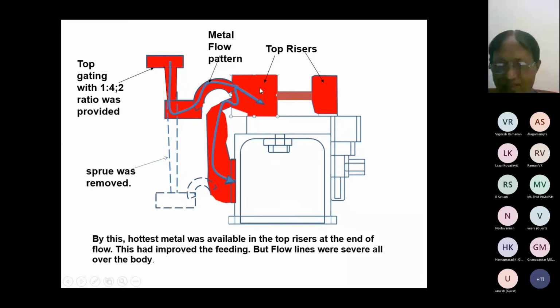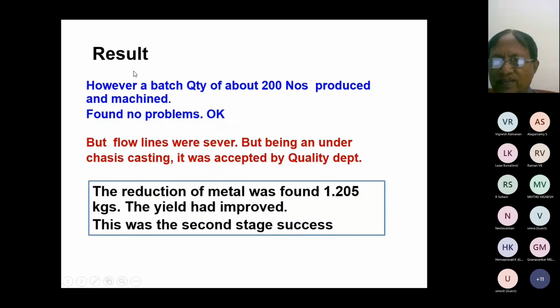But there were flow lines. Here and here, flow lines are mixing up over there. But for the flow lines, no other defect was seen. However, a batch quantity of about 200 numbers were produced and machined, found no problem at all. The flow lines were severe, but being an under chassis casting, it was accepted by the quality department.